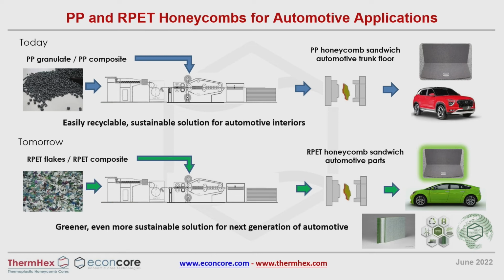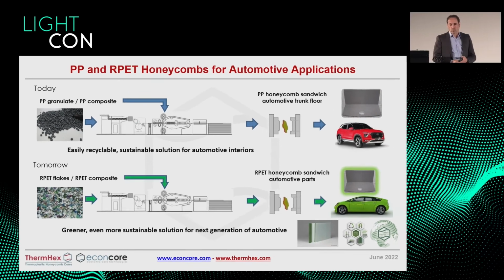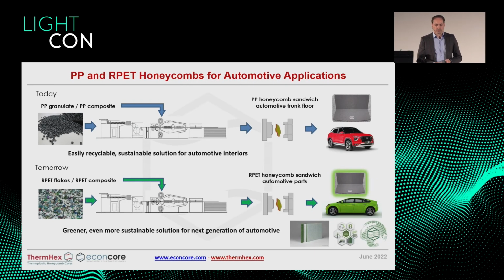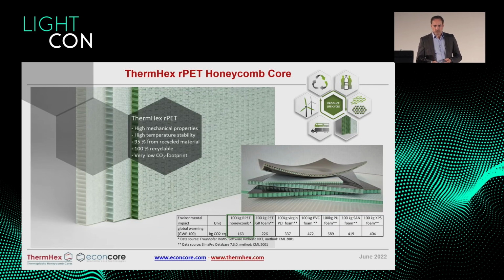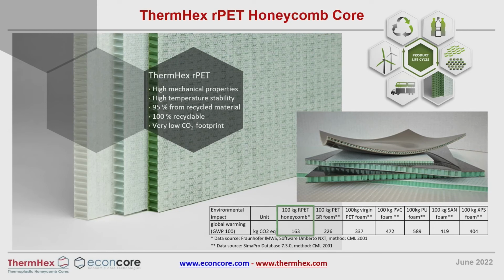This is the next step for us. We are currently producing from polypropylene granulate the polypropylene honeycomb, and then glass fiber polypropylene skins for these parts, and are in development of a honeycomb core based on recycled PET flakes from packaging grade, so not bottle grade, can be even from recycled bottles, which are then used in packaging first. So very low-cost flake material we can use because it doesn't need to be transparent. And we can process this to form the honeycomb core and then automotive parts. So this has a very low CO2 footprint, much lower than foam cores, and can be completely recycled.